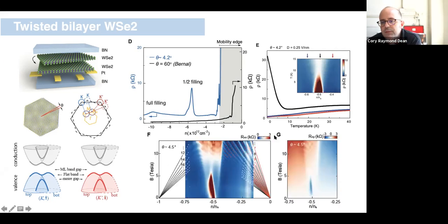The way we do that is from Hall measurements, and really in these devices, we were able to identify essentially Shubnikov-de Haas oscillations near formation of quantum Hall states at high enough field. And we can identify these kind of Landau fans, and we can project those Landau fans back to precise density points at zero field. And that allows us to identify really in a fairly precise way band fillings.